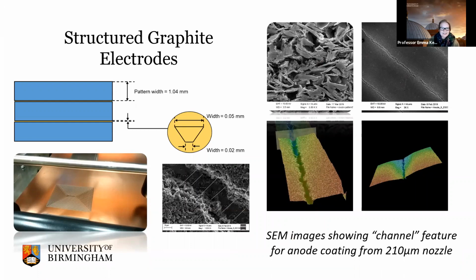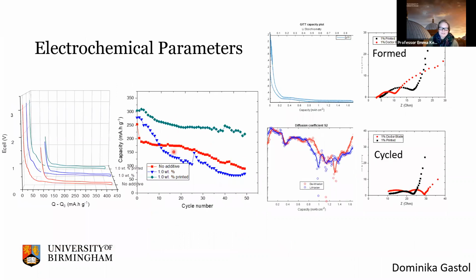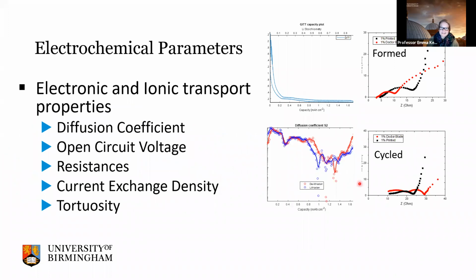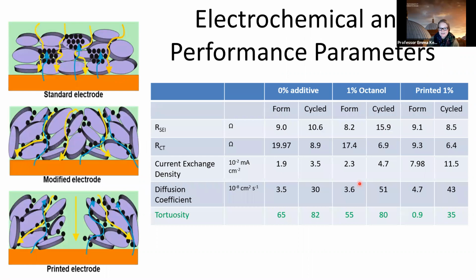So finally, one of the things I wanted to mention was that we can now analyze these electrode properties for some of their parameters. And we're looking at not only cycle life, which we can improve here, as you can see from the printed electrodes, but also we can look at the diffusion properties and some of the kinetics and the current exchange densities, which we can extract from some of the EIS data. And this data is quite important because we can use that in optimizing our performance properties of our electrodes. And this is something that we're also using for input into multi-physics models along with Imperial as well. So we're providing some of those parameters to go into those multi-physics models.